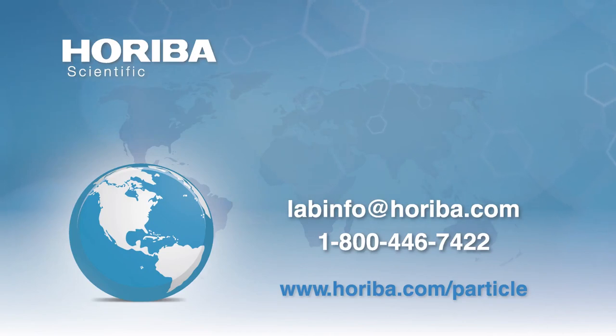So we got two more questions. One is, does TiO2 for sunscreen require the same size for paint? Both applications are for hiding surfaces behind the coating. Okay, so TiO2 for sunscreen, the particle size of that TiO2 is below 0.1 micron. And people just don't like to walk around on the beach looking like a painted clown. So you purposely make the TiO2 small so that it is transparent and the light is not bending.